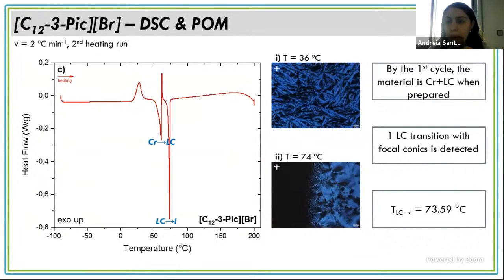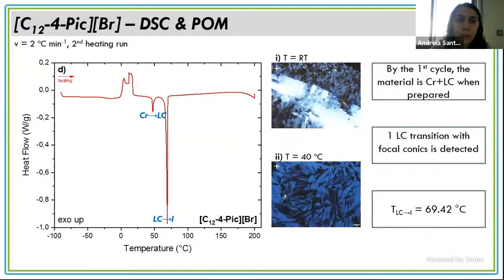For C12 3-picolinium bromide, in the first cycle, the material is a mixture between crystal and liquid crystal when prepared, having focal conics detected by POM, which are characteristic of smectic phase, and in the second heating, 1 transition was detected, having a small liquid crystalline window. For C12 4-picolinium bromide, as the previous material, in the first cycle it is a mixture between crystal and liquid crystal when prepared, having focal conics detected by POM, and in the second heating, only 1 LC transition was detected with a small LC window. The isotropization is at 70 degrees.